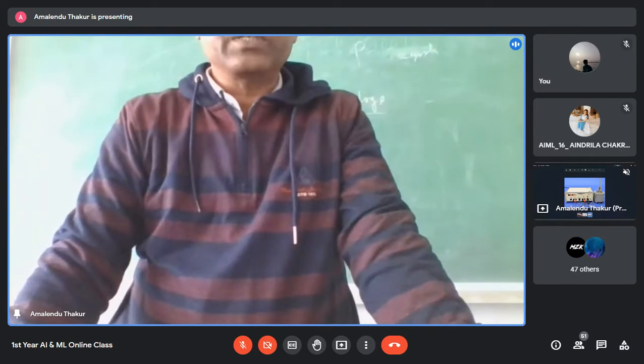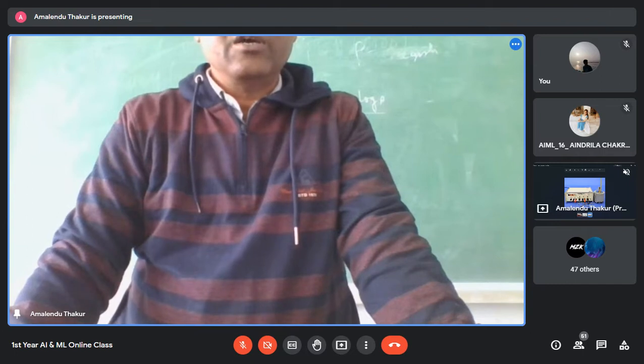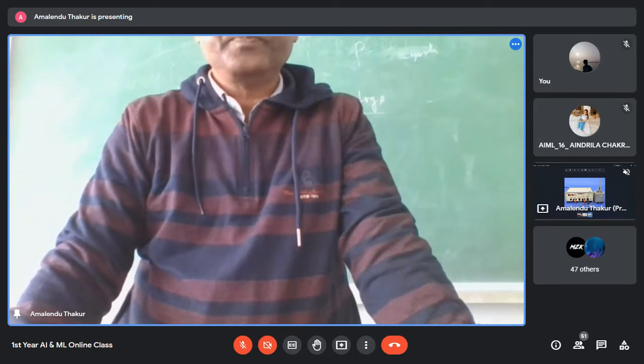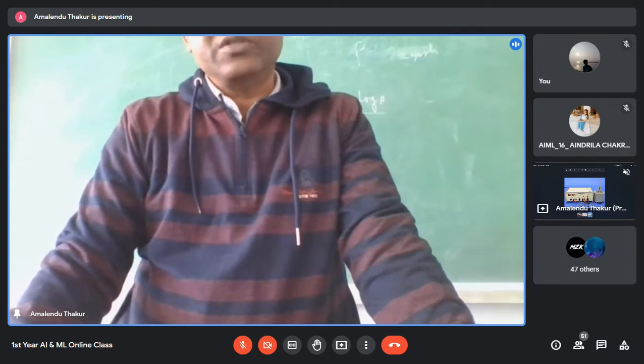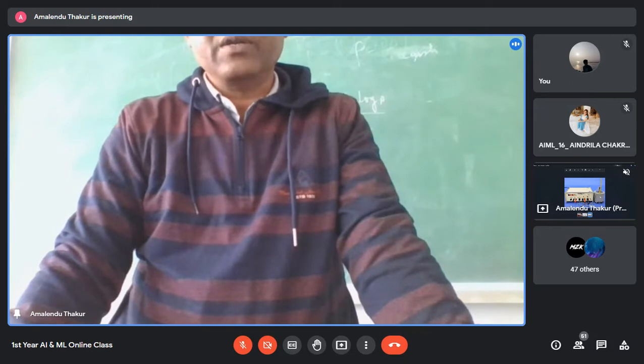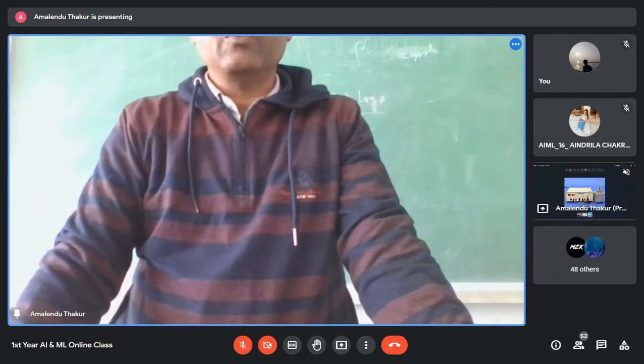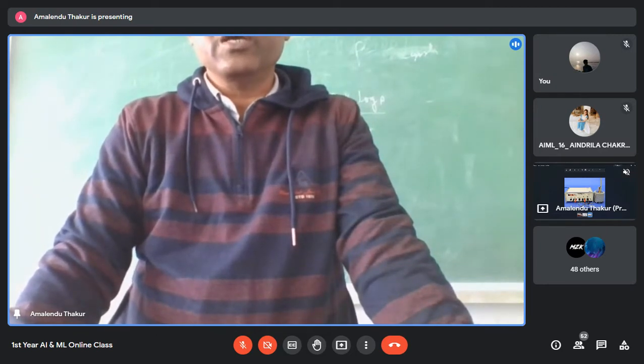In this setup, this is a 4-port setup. From this setup, we supply the current as well as we measure the current and voltage to the 4-port system. This is an oven. The resistivity changes with temperature. That's why we use an oven. The oven is connected with the system, so the temperature can be increased, and we can measure the temperature using a thermometer, which is inserted within the oven.